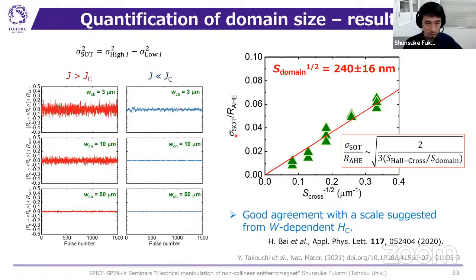And this shows the main results. So the fluctuation level was normalized by the full scale of the Hall resistance change, and we plot it as a function of the inverse of the square root of the cross area of the Hall device. So as you can see, the linear relation was observed, and from the fitting, we could estimate the domain scale to be around 240 nanometers.